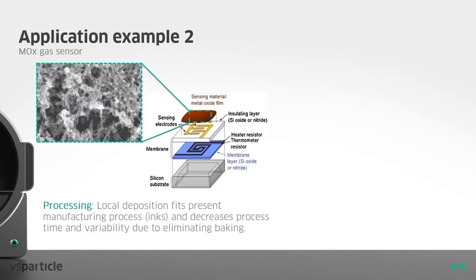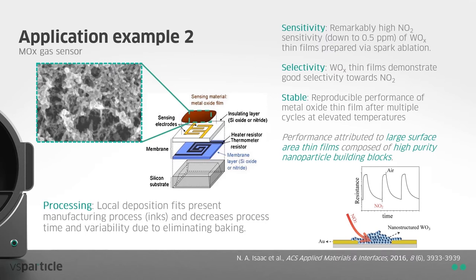The second application is the development of metal oxide gas sensors. We can locally deposit gas-phase metal oxide nanoparticles directly onto a sensor chip, allowing us to easily prepare gas sensors without the use of inks or any post-processing steps. A recent publication demonstrated how spark ablation could be used to prepare highly sensitive, selective, and stable tungsten oxide-based sensors for NO2 detection, attributing their remarkable performance to the large surface area of thin films composed of high-purity nanoparticle building blocks.